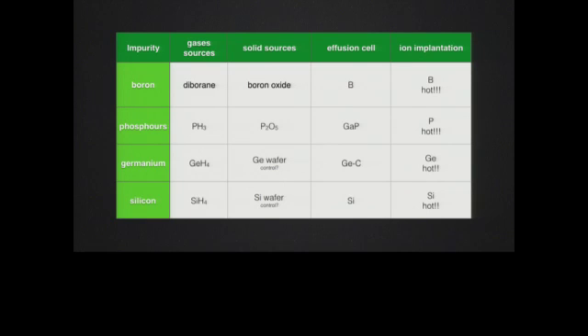So if we want to put some of these impurities in there, how can we do that? Well, we have gaseous sources, we have some solid sources, and one thing that we've developed is a new effusion cell. These are cells that are typically used for MBE growth. The reason is that one of the best n-type dopants is phosphorus, and the source of phosphorus is phosphine, which is, of course, a pretty toxic material, and we don't want any of our students handling that. So we have been developing a gallium phosphide effusion cell.